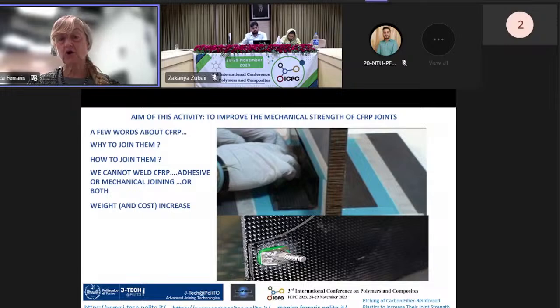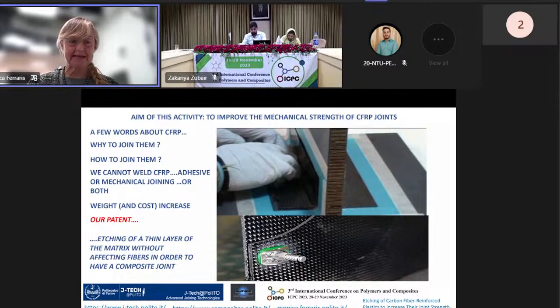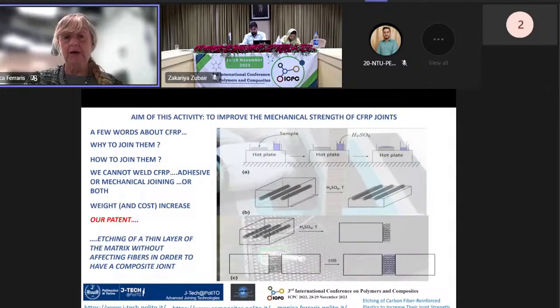Weight increase and cost. So in order to avoid both of these and have a reliable joining strength, we patented a method to etch a thin layer of the matrix without affecting the fibers, in order to create a sort of composite joint.